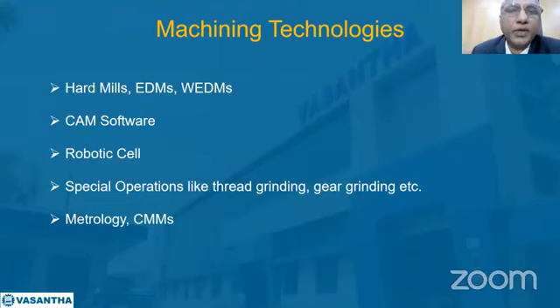And then the mold base needs to be a pre-hardened stainless steel mold base. When you make these kinds of molds, the inserts are hard. After the heat treatment, if you use normal CNC mills, they will not work, meaning the surface finish would be very rough and the accuracies will not be enough.